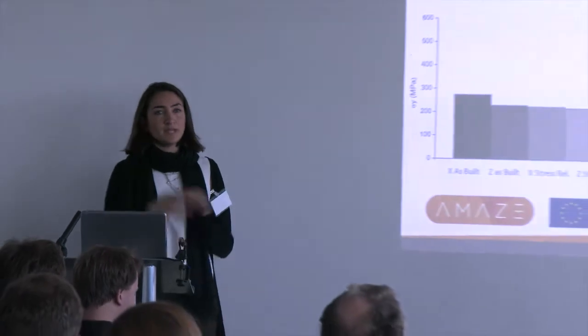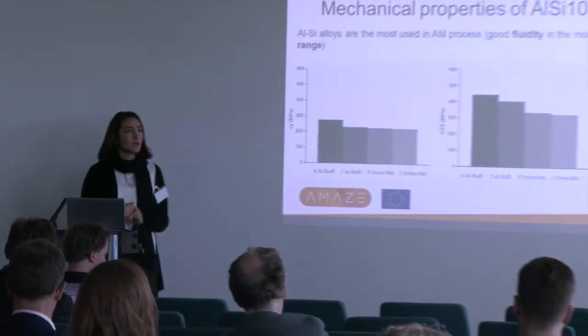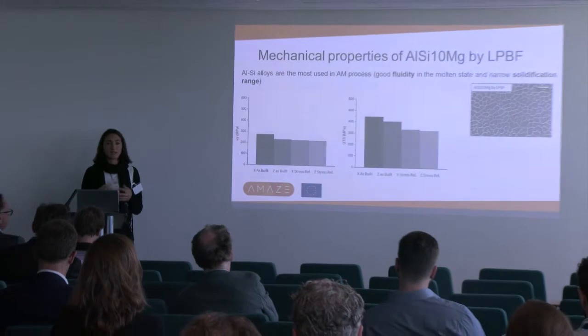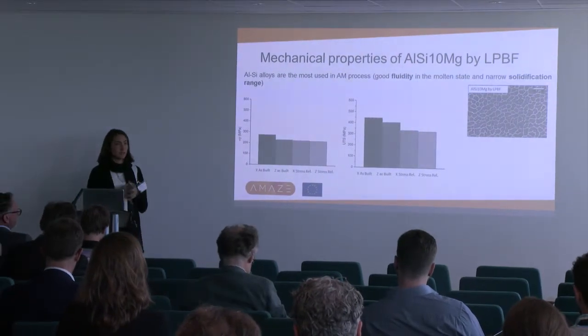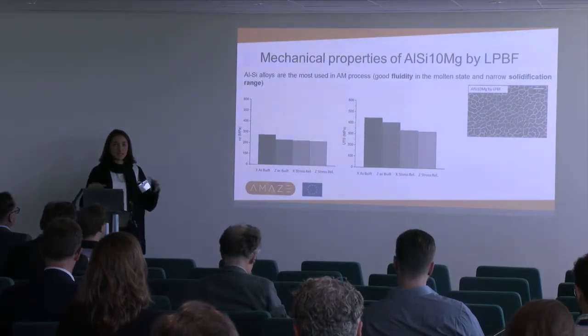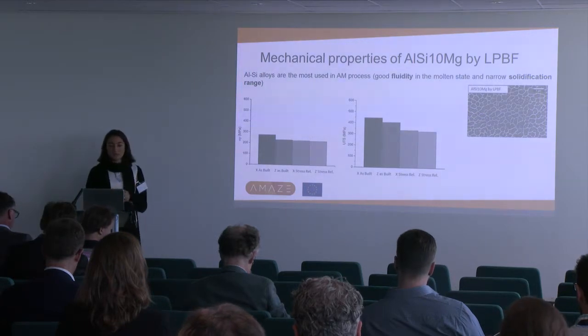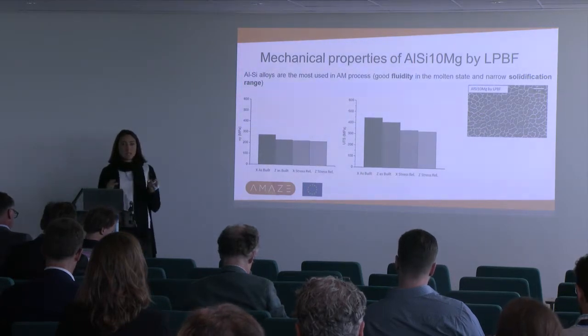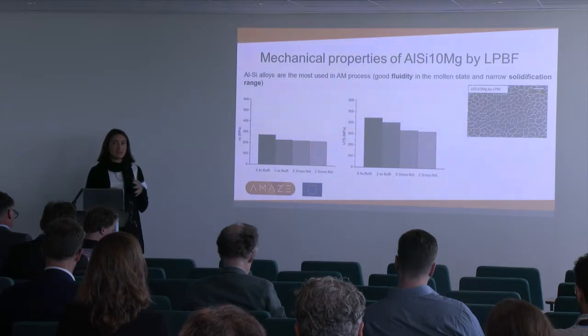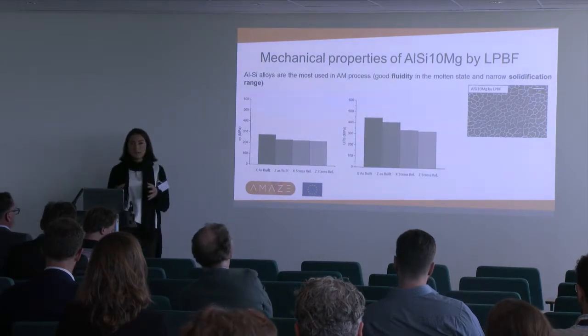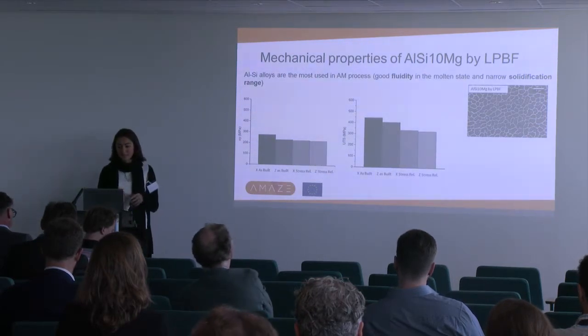So only as an introduction, the most used aluminum alloy in additive manufacturing is the aluminum silicon 10 magnesium alloy, or mainly the aluminum silicon alloy. Why? Because silicon gives a good fluidity in the molten state to the alloy, so the molten pool can spread, and we have a good consolidation. And then also because we have a small, narrow solidification range, which allows us to have crack-free samples.